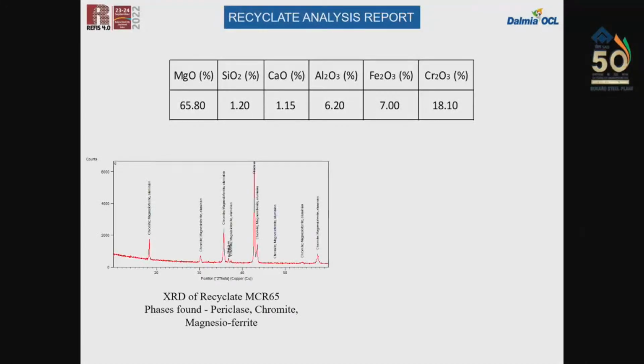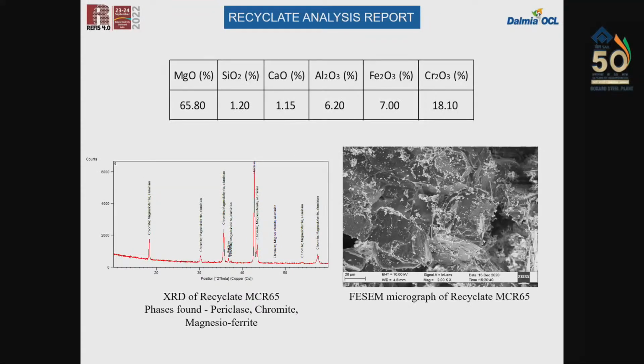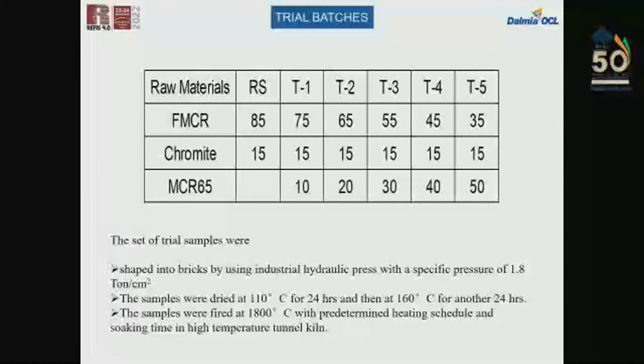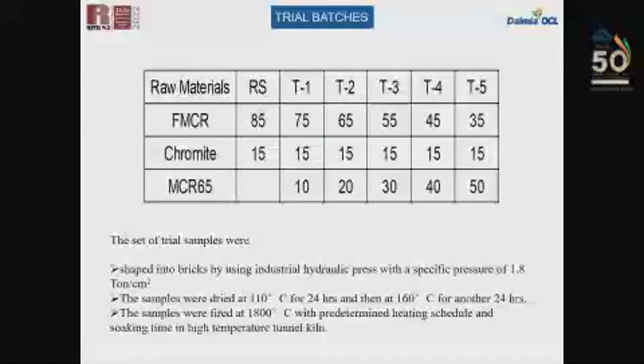In the XRD, we have found all the phases, like the periclase phase, chromite and magnesioferrite. No low melting phases. This is the morphology of the recyclate, which we name MCR. We made 5 batches where we have used this recyclate material. We have made bricks and fired them at a very high temperature in a tunnel kiln.